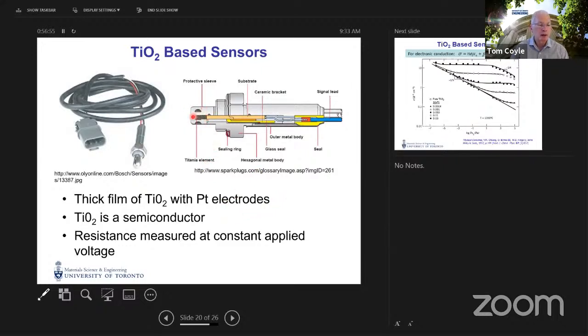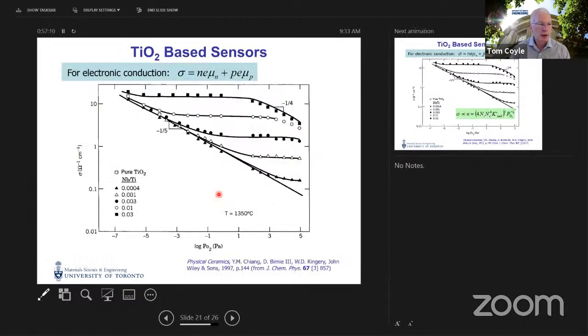We'll expose that sample of TiO2 to various oxygen partial pressures and see what the conductivity is. So here's some experimental results for exactly that type of experiment. Pure TiO2, which is what our defect creation reactions described, is given by these open squares, and so this straight line. And what we see is that over several orders of magnitude of oxygen partial pressure, the conductivity, in fact, varies as PO2 to the -1/6.